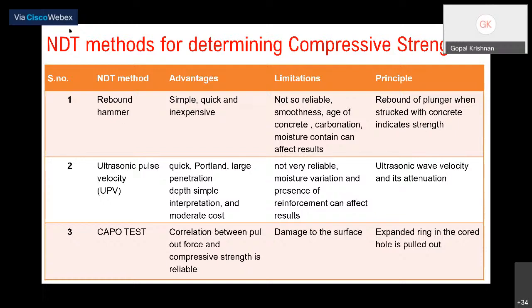So when you want to understand the compressive strength, NDT methods for compressive strength property, a simple and quick method is the rebound hammer. And to understand the integrity and homogeneity, we use the ultrasonic pulse velocity. And with the CAPO test, we can get a quick strength. Instead of doing a core and waiting many days to get the strength, the CAPO test will help you get the strength quickly. Maybe 20 minutes you can spend to do the test at the field. Then and there you can get the strength of that particular concrete or member.